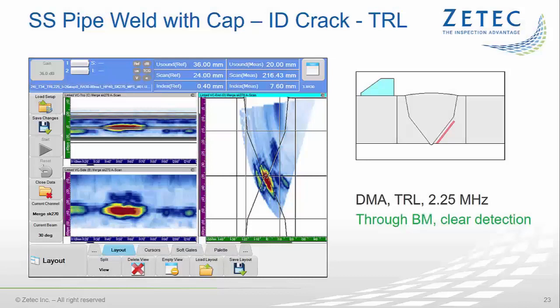Then let's take a look at the L wave examination data. This slide shows merged data from 30 to 85 degrees obtained with the Zetec DMA probe at 2.25 MHz in TRL mode. The crack is on the near side of the weld, and the image from the L wave beam clearly shows a corner trap signal and very well resolved tip signals. The ID crack is very well detected. The signal to noise ratio was measured at 17 dBs.